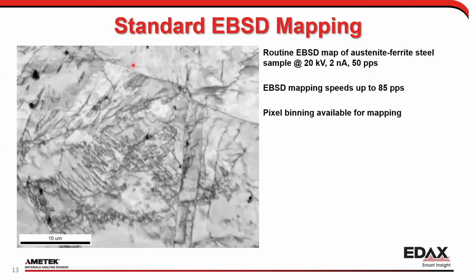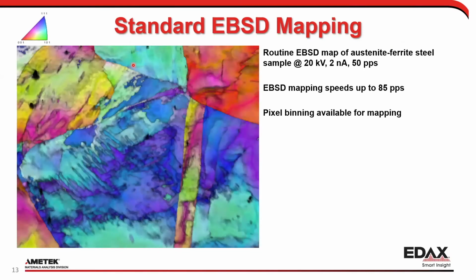So it works for standard EBSD mapping. Here's an austenitic ferrite sample with 2 nanoamps at 50 points per second, and you can see it maps. Again, it gives incredibly pretty maps for this kind of stuff, but also incredibly precise because of what it's doing.